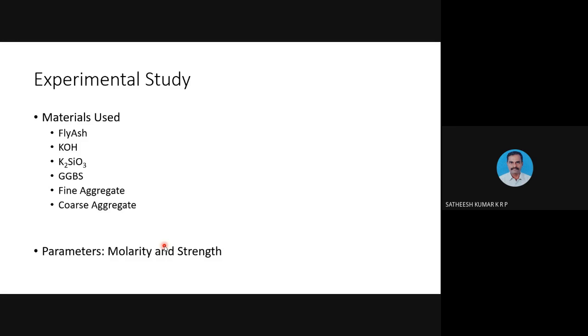From this slide onward, I will try to explain the experimental study which we conducted in our institute. We were trying to explore the use of fly ash with GGBS. We used a small percentage, around 10%, of fly ash with the GGBS. The solutions which we used are sodium hydroxide or potassium hydroxide, as well as sodium silicate or potassium silicate. We were not going for calcium hydroxide and calcium silicate solutions. That is also possible, but the reaction takes place very fast and it will leave residues. The intended product won't be obtainable with calcium compounds.